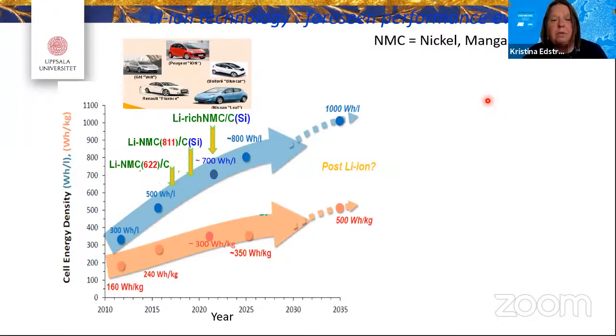So if you look at the projection of why this is a competition, you can see on the different nickel, manganese, cobalt materials, they are called NMC for battery nerds. And the composition is 6 nickel, 2 manganese, 2 cobalt. You get a certain composition. And when you try to increase the amount of nickel and reduce the amount of cobalt, you actually increase the capacity. And you can make even special structures of this and increase the capacity even more. And what Tesla is now trying to do is to go even further by removing the cobalt.